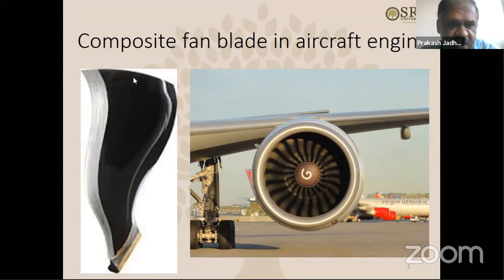And width is approximately 0.4 meter or something. And thickness ranges from 10 to 20 millimeter. So actually thickness varies all around the cross section, okay? If you cut the fan blade and see the cross section, you will see that at the tip, the thickness is almost zero, maybe 1 or 2 millimeter at the tips, at the left edge and the right edge.